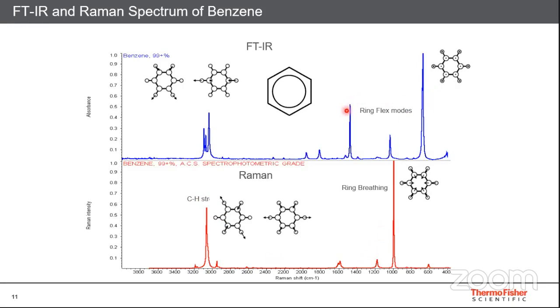The ring flex modes are seen in infrared spectroscopy. They absorb in the infrared region, while the ring breathing, where all the carbon atoms are going inward and then coming outside, a kind of breathing effect, you can see in the Raman. You see a peak at around 1000 centimeter inverse in the Raman spectroscopy, which also confirms the ring structure of benzene. So this is how infrared spectroscopy and Raman spectroscopy can be used as complementary tools to get more information of your molecule.